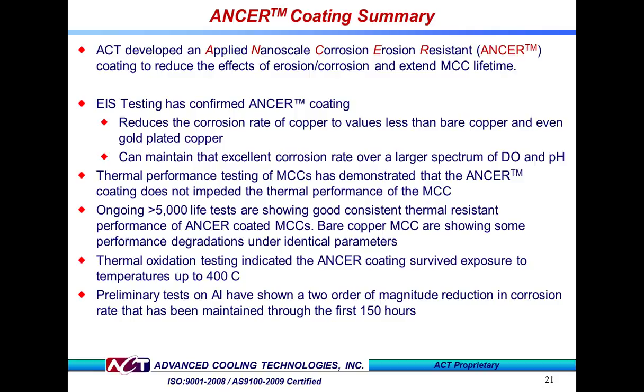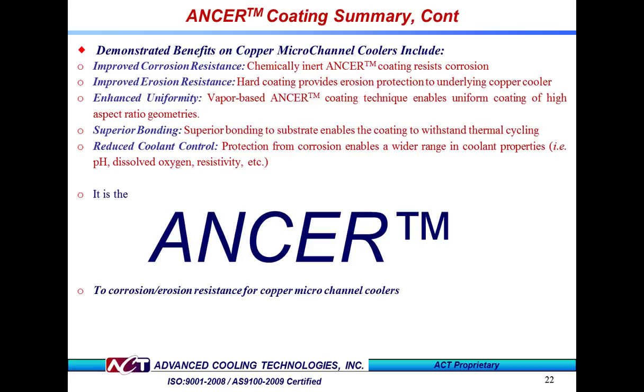Ongoing 5,000-hour testing demonstrated that the ANCER-coated MCCs maintain consistent thermal resistance, while bare copper MCCs are showing some degradation under identical conditions. Preliminary results on aluminum have demonstrated 2 orders of magnitude improvement in corrosion rate in initial testing. Based on these results, we are confident in saying